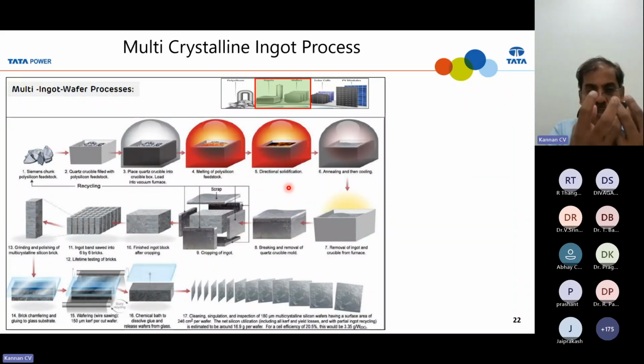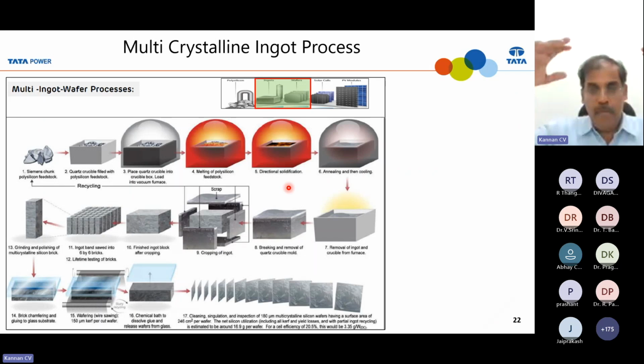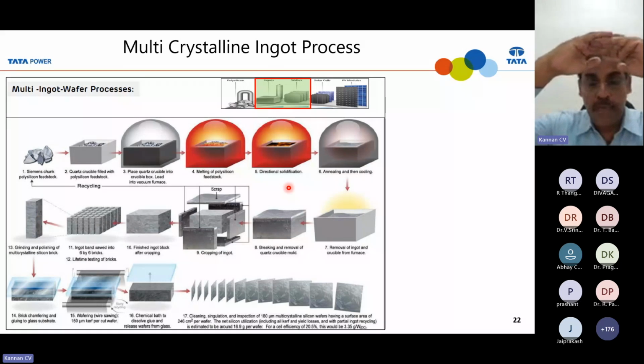So the crystallization starts from the bottom, then the interface will move from bottom to top. So the solid liquid interface moves from the bottom, then it slowly moves, because we are extracting the heat through the bottom through some cooling plate, so that because of the temperature gradient, the bottom side will become crystalline and the top side will be molten. That solid liquid interface will move from bottom to top. Automatically the crystal grows slowly, something like that, right?